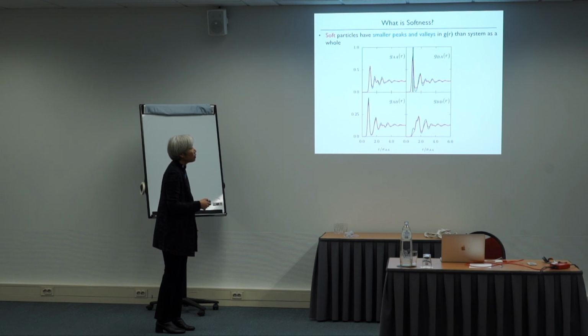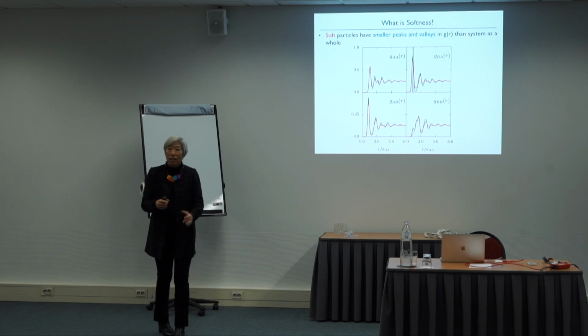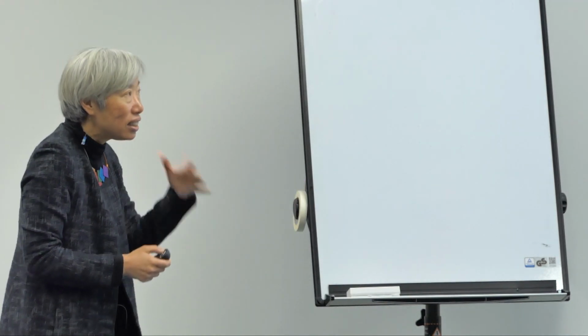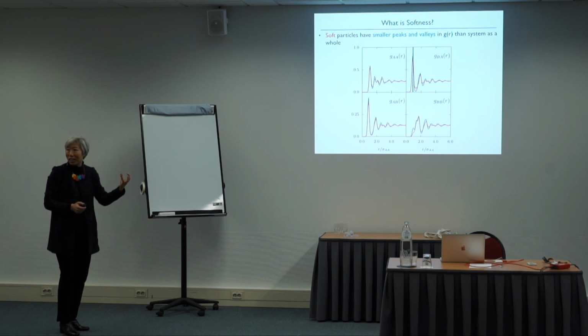If I average over all of those, what does their pair correlation function look like compared to all of them? The difference is tiny. But the difference is that soft particles have a lower first peak and a higher first valley. What that means is that they have fewer neighbors surrounding them, so it's easier for them to get out. There's this old picture of things rattling around in a cage. This is a way of quantifying a very old idea in the glass literature, the idea of particles being trapped in a cage. This softness is telling you the strength of the cage.